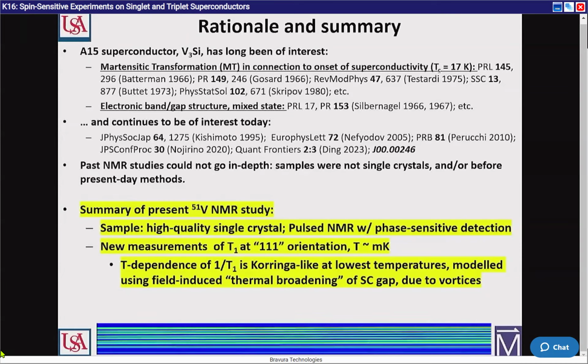Korringa-like behavior of 1 over T1 at lowest temperatures and field dependent, kind of like what the previous speaker was describing. But in our case, we believe it's field-induced thermal broadening of the gap. Yes, due to vortices.